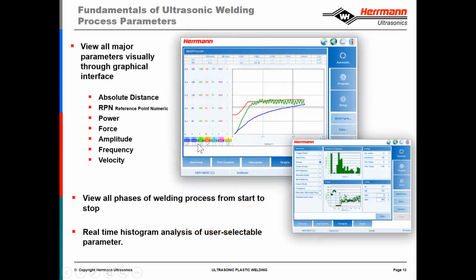So here's a close-up of what the screen looks like that we use for programming and for process control and for quality control. On the graph, we can display various things: absolute distance, which is where the final point in space is after welding, RPN, or the amount of collapse that the parts went through, how much power was consumed, how much force was applied, what amplitude, what frequency, and most importantly, the velocity. So you can see here this blue line is the joining velocity curve, and this is almost ideal.